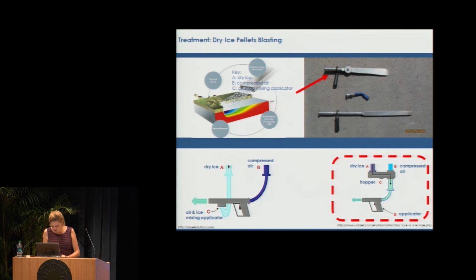In a single hose system, there's one hose going from the machine to the applicator, and there is a feeder system that feeds the dry ice particles and compressed air into that single hose. So the dry ice particles are accelerated by the compressed air stream through the entire length of the hose, so they have a lot of time to accelerate. That's why it becomes a bit more aggressive technique than when you only add the dry ice pellets near the end. Then you have a shorter time to accelerate, so this is a less aggressive technique.